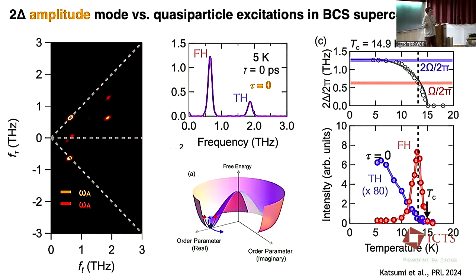But in nonlinear responses, I can do experiments, for instance, where I excite the system, I can de-excite the system, I let it time evolve in between, and then I can excite it again, and then I can watch the system decay. I might excite it again, and then de-excite it, and then watch it decay. All of these, the chemists would call Liouville pathways. And as far as we're concerned, each of these different processes gives us different ways of interrogating the system, and we can get different information out about it. It all sounds complicated, and it is.